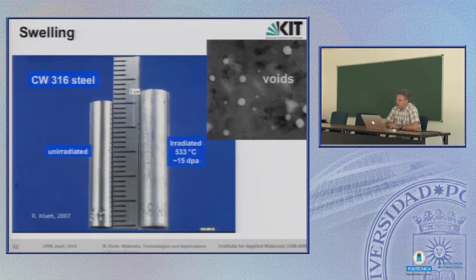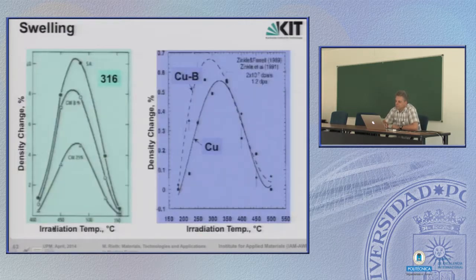Now let's have a look at the swelling behavior. First, in terms of irradiation temperature, and you see here, also for the case of austenitic stainless steel, there is a maximum effect in a certain temperature range, in this case between 450 and 500 C. There is the swelling peak where the material obviously forms the most and biggest stable voids. If the material was cold worked, and cold working stainless steel means you increase the dislocation density, you introduce a lot of dislocation networks, then swelling is not as pronounced.